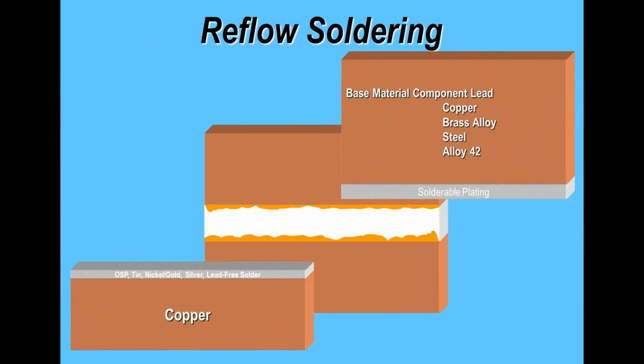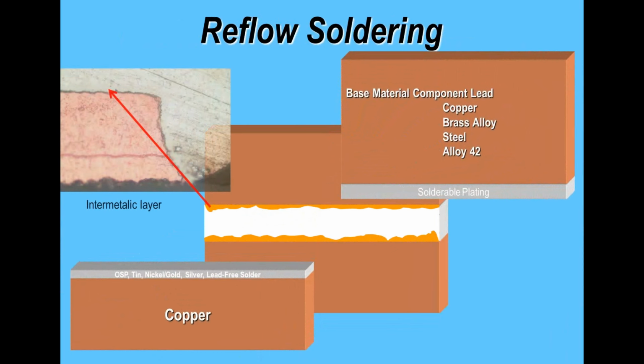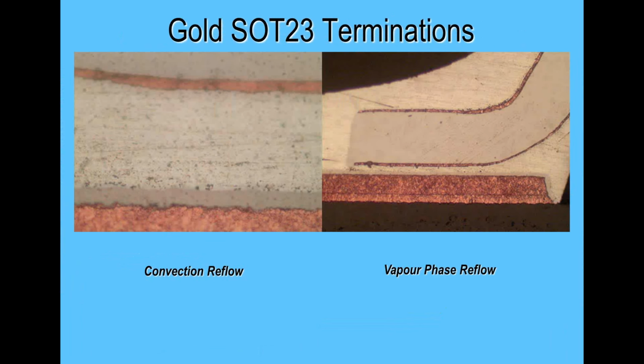So when you look at a microsection, you'll normally see these layers. In the microsection I show on this slide, you can see we formed an intermetallic layer between the copper and the solder, and it's just about visible between the bulk of the solder. Here it's a lot more obvious, and these are again solder joints formed on a gold substrate. They happen to be produced with two different processes, convection reflow and vapor phase reflow, but forget about that for the moment and just look for the solder formation.